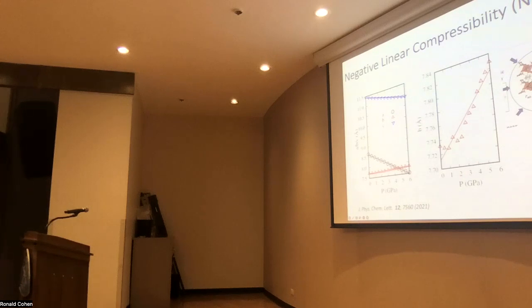But if we take a look at the B lattice parameter, it actually shows the opposite trend. The B lattice parameter increases in response to the hydrostatic pressure, which is known as negative linear compressibility. So this material, in fact, exhibits negative linear compressibility. This is the zoomed-in plot, and we can see that first it starts with the usual positive compressibility, and then it changes sign.